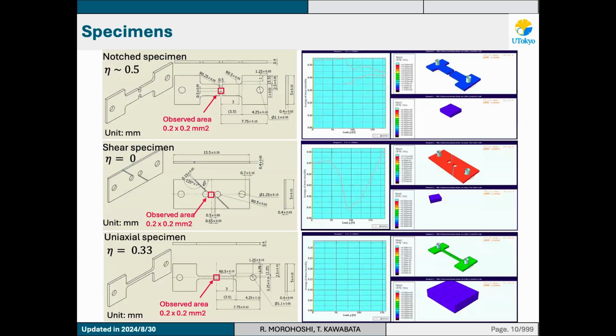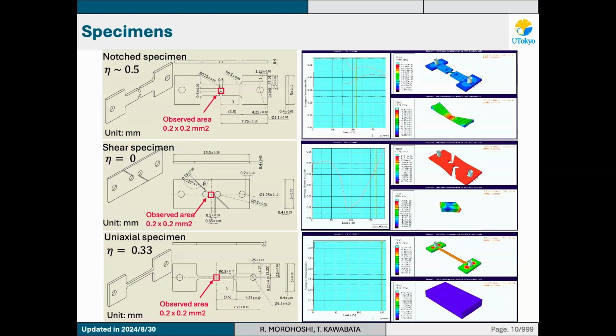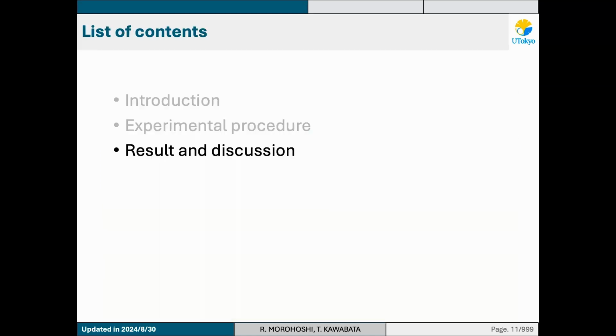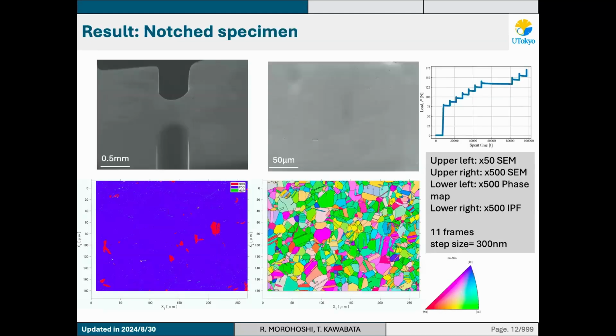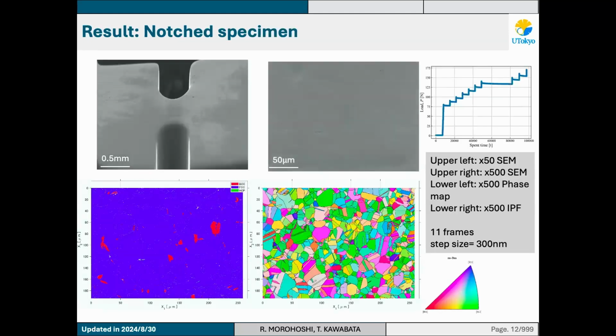And this is the specimen that we use. We arranged 3 kinds of specimen, each having a different stress triaxiality: 0.5, 0.0, and 0.33. We call each specimen the notch specimen, shear specimen, and uniaxial one. And next is about the results and discussion. First, this is the result in the notch specimen.